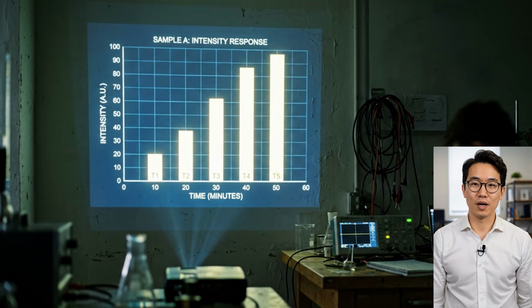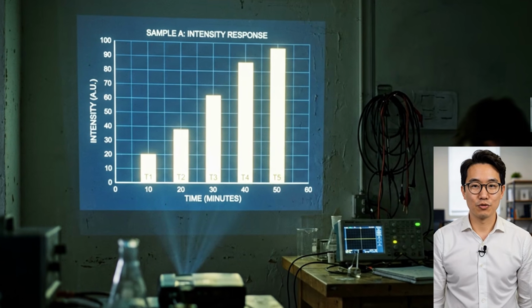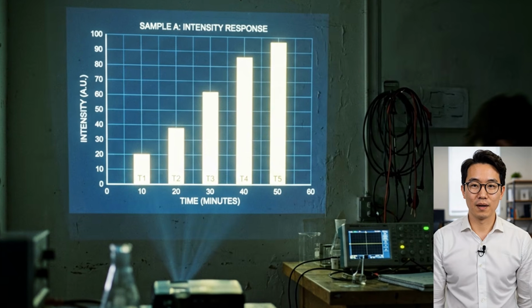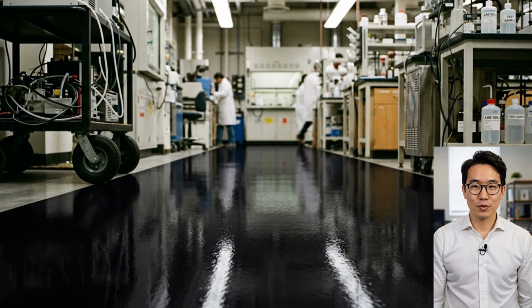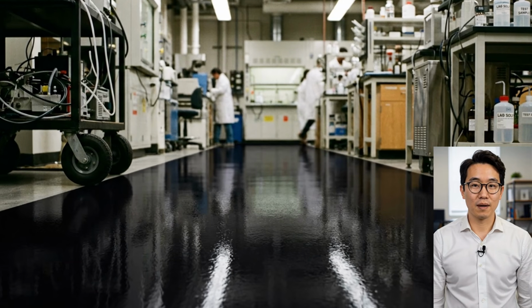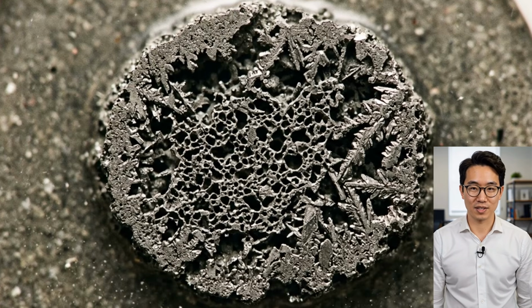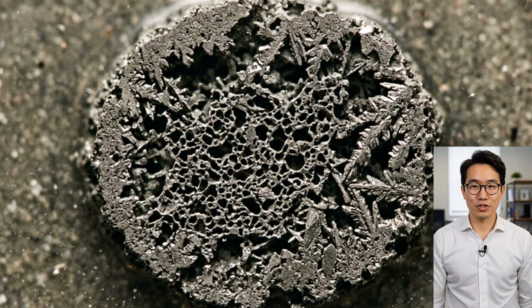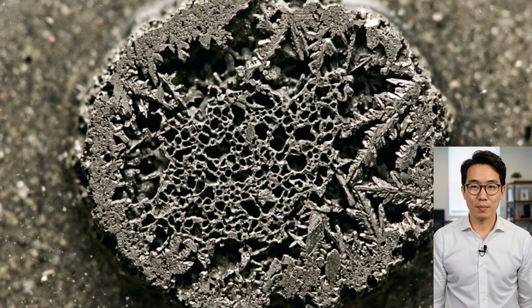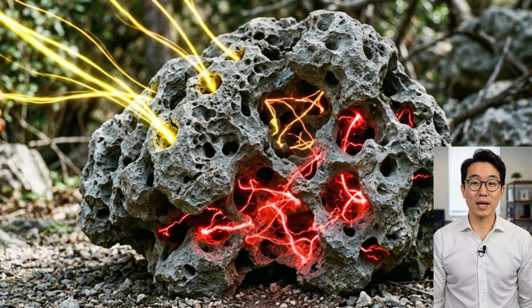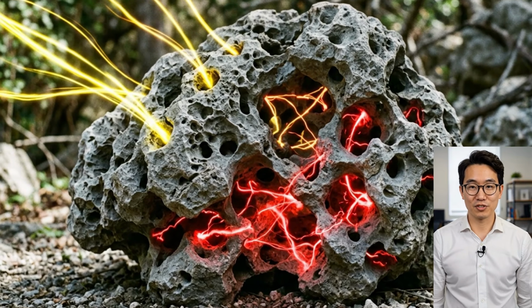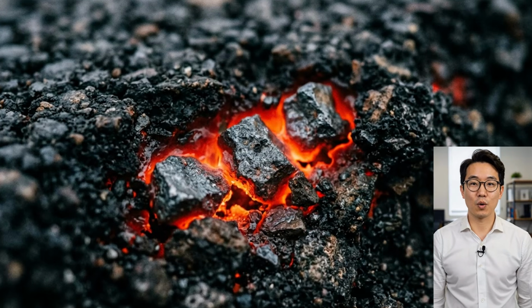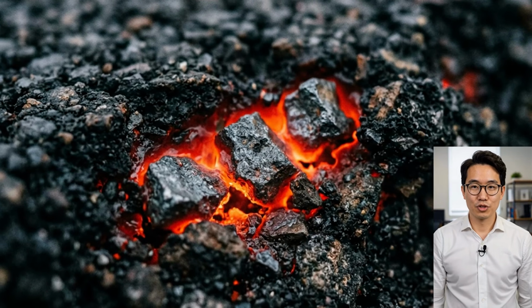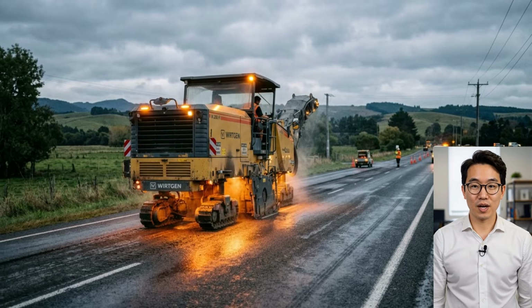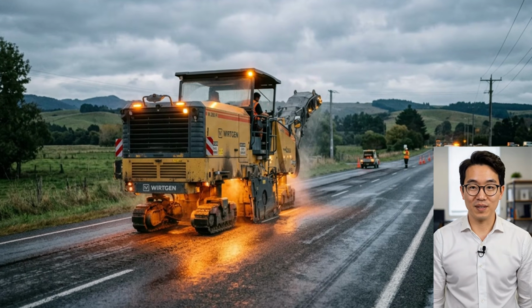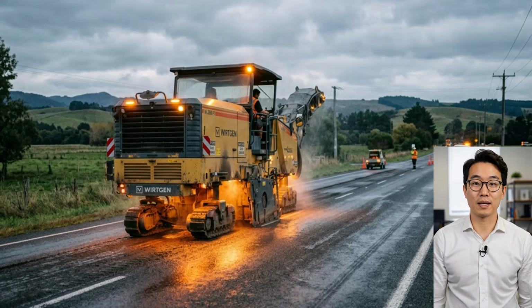The same study also found clear healing gains. When conventional filler was partly replaced with steel slag powder, the healing index improved by 8.7%, 17.3%, 22.1%, 26.9%, and 27.7% across different replacement levels. The best gains came near the higher end. What makes that possible is the porous inner structure of steel slag. Porous just means full of tiny holes, like the little pockets inside a sponge. Microwave energy enters, bounces around, loses itself inside the material, and turns into heat instead of escaping so quickly.